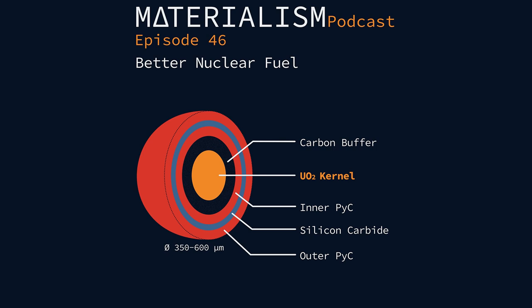So that led to interest in oxide kernels. And these radically simplified the fabrication process because they didn't have to worry about oxidation as much. They also maintained better chemical stability during the fabrication process. So they were a bit safer. One of the other benefits is that a lot of the heavy metals that are produced during fission can form oxides. And so if you want to try to prevent these from attacking your silicon carbide layer, it makes sense to neutralize them in the form of an oxide. And this was great, but as they started to test these more and more, they noticed a few problems. As you go to higher temperatures and irradiations, the oxygen potential tends to increase quite dramatically.